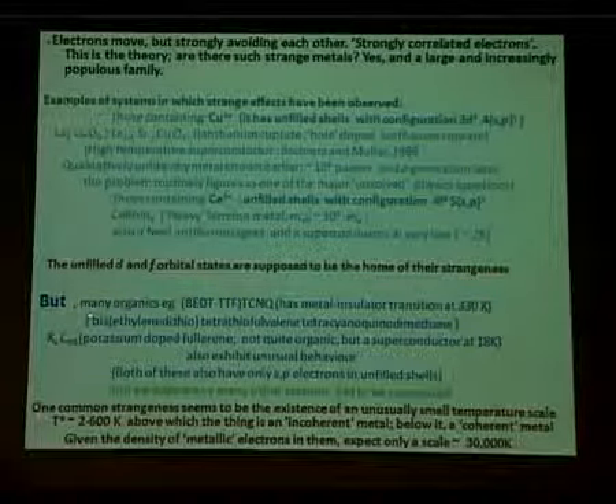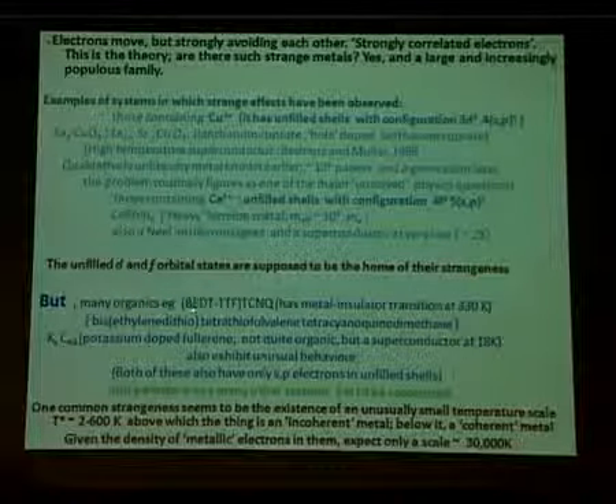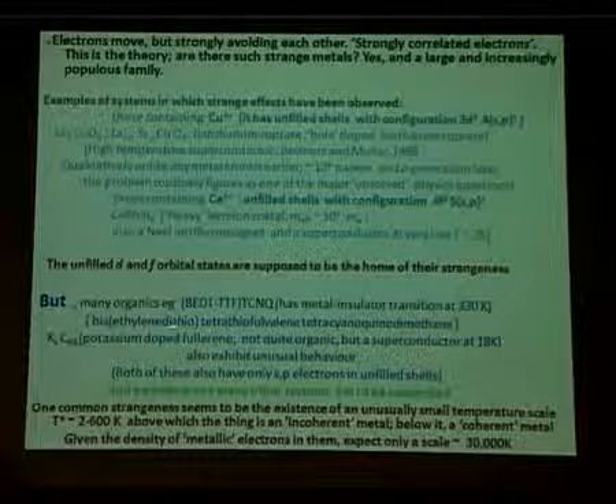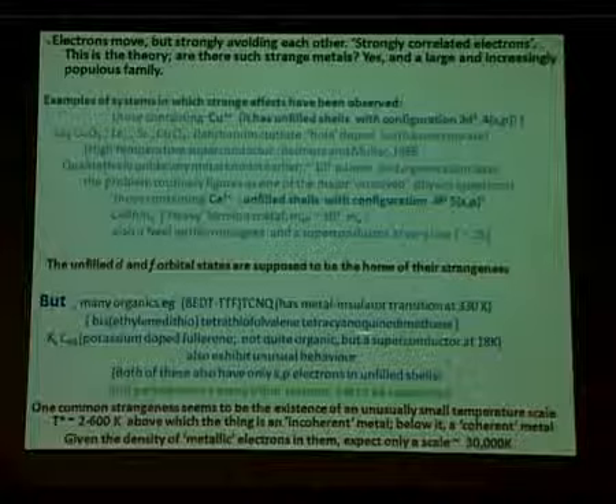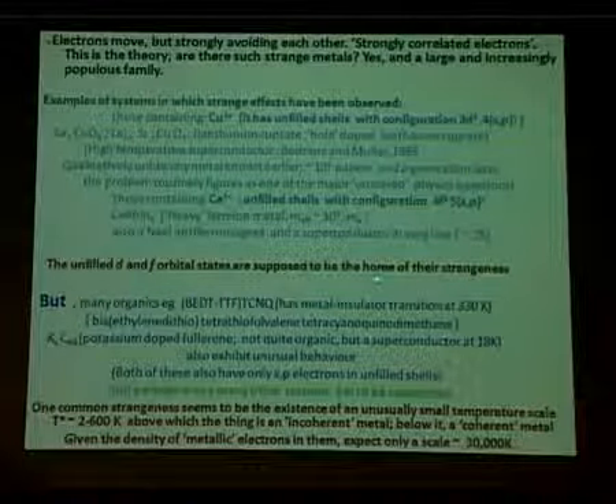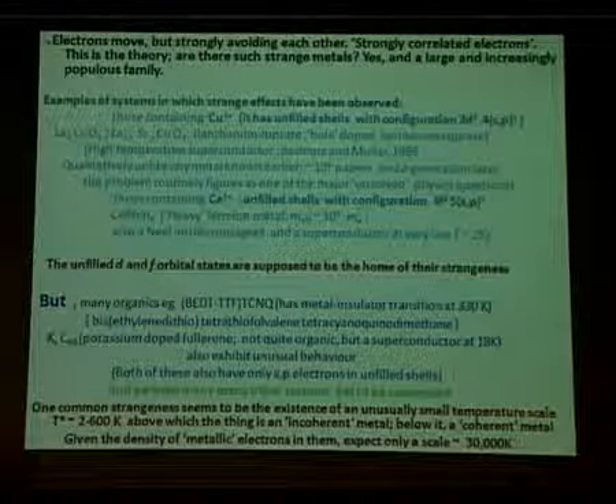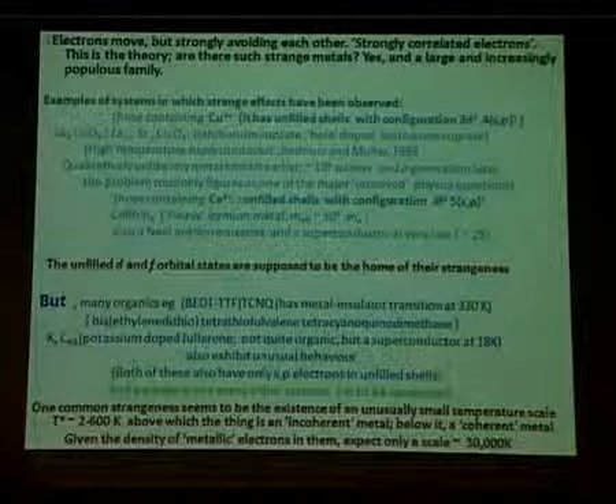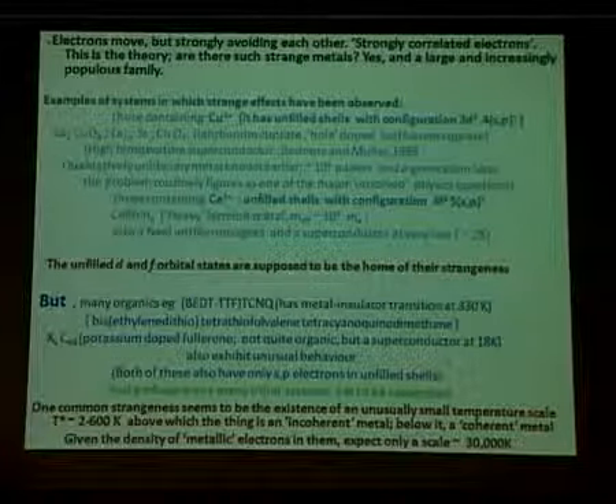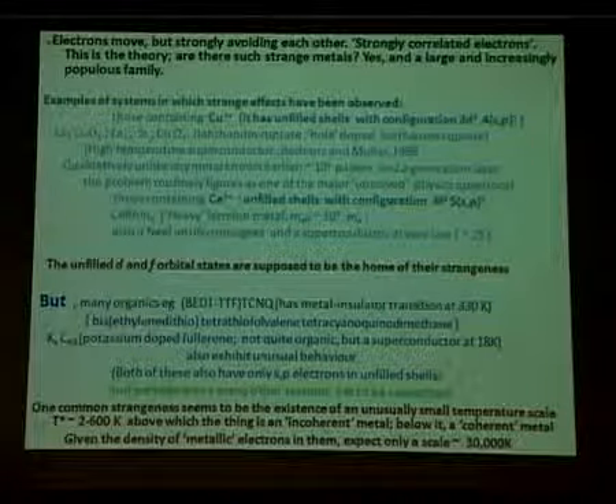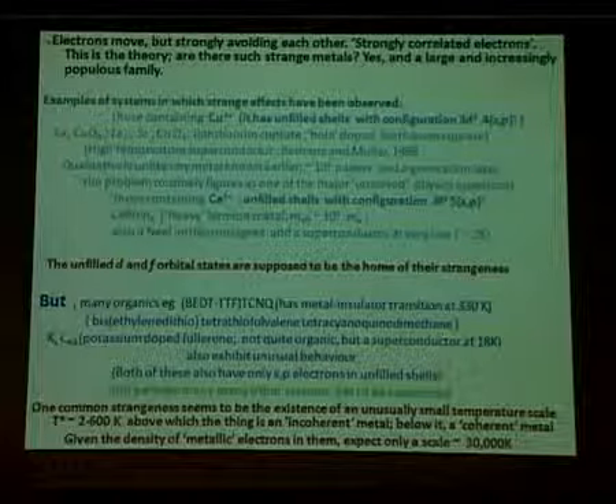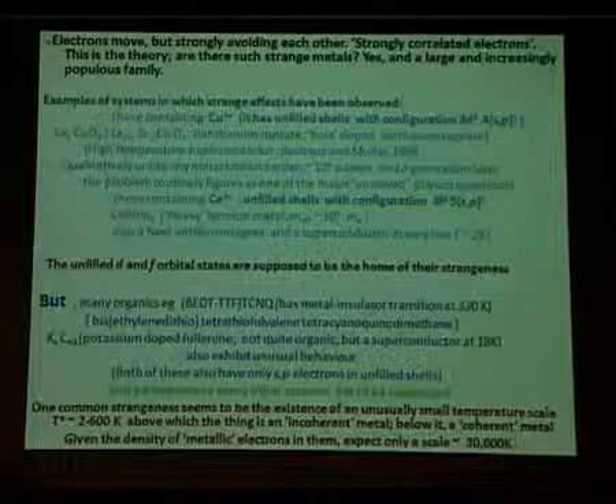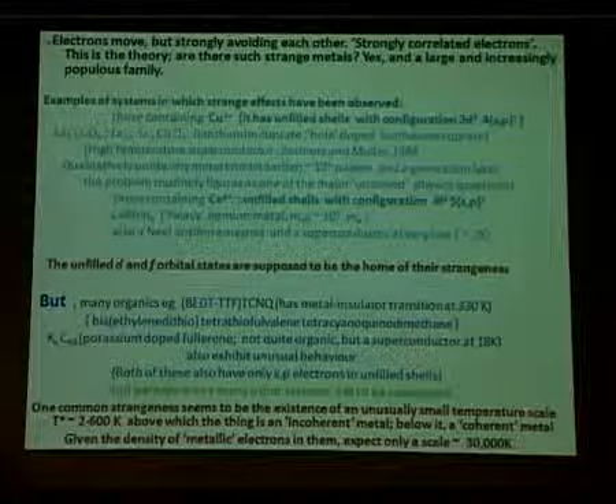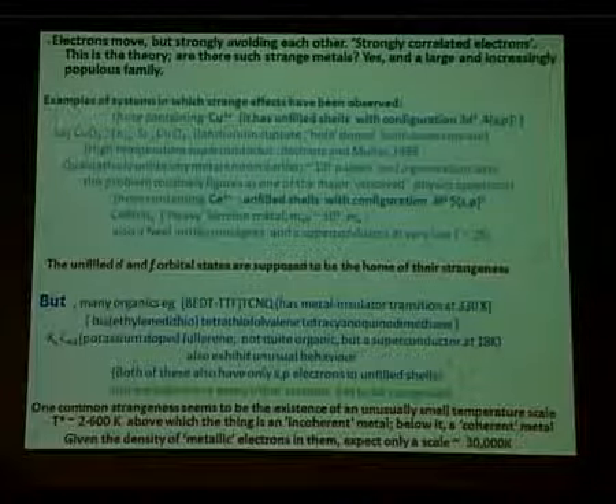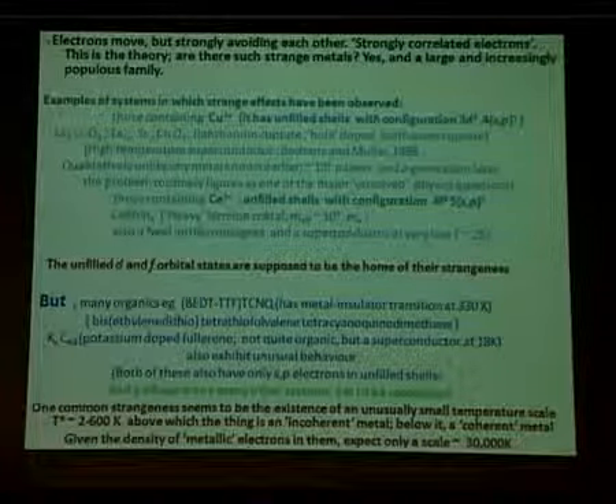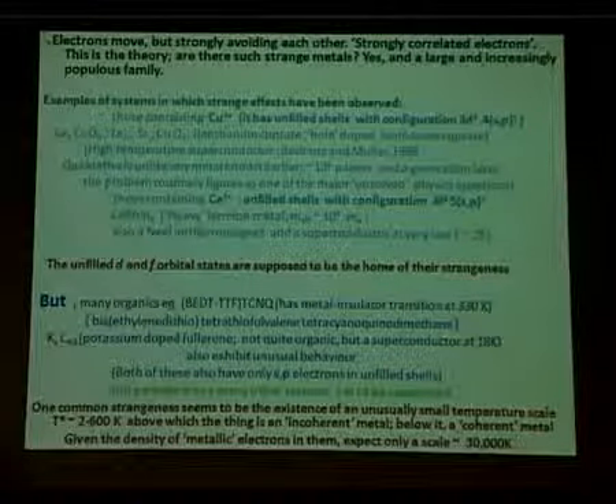You see, I mentioned here two examples. One is an organic compound which we write as BEDT-TTF-TCNQ, whose full form is long, which I don't want to pronounce. This thing has a metal insulator transition at 330 Kelvin. This metal insulator transition means something very strange also: the electrons in this system below a certain temperature don't move, and above a certain temperature they move, and all together. So this generally doesn't happen. Many people believe that is because of strong correlation, that is, the fact that electrons have a tendency, because of the strong local repulsions, to stay wherever they are. So that is one example.